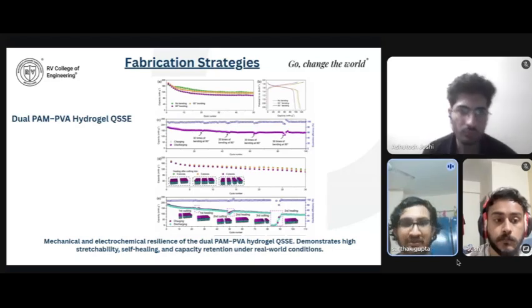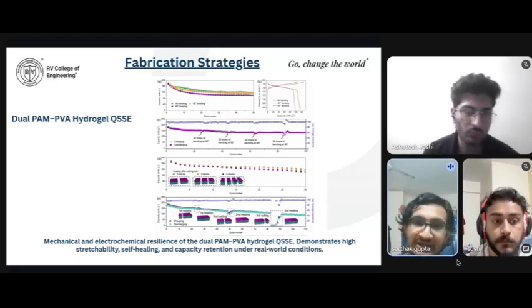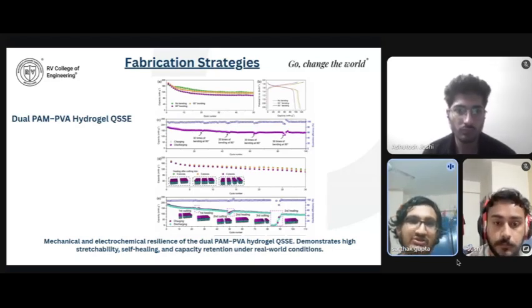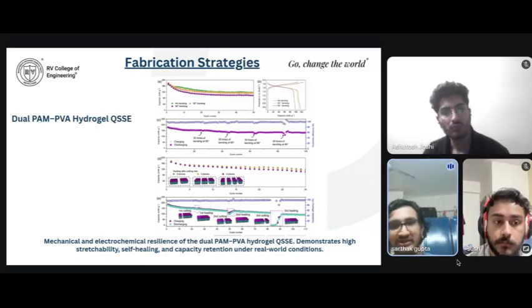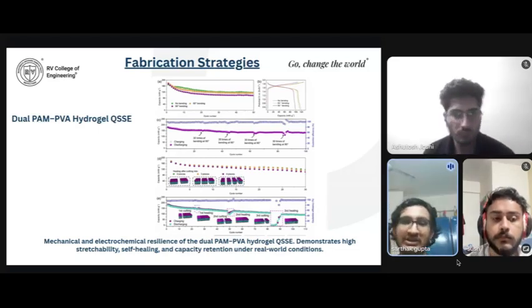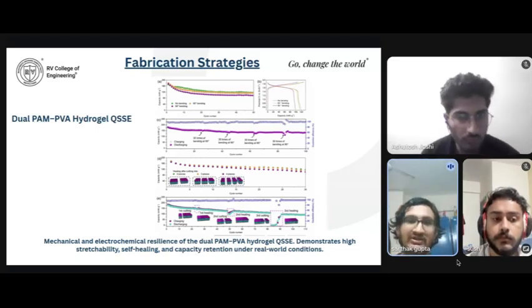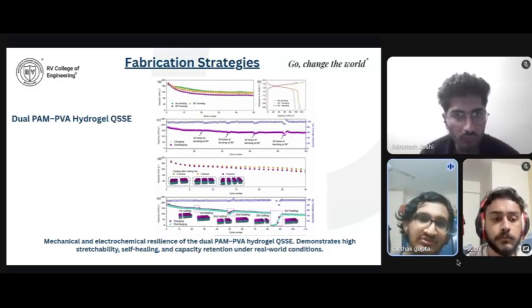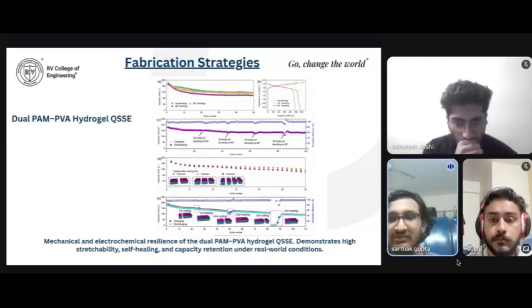Then coming to the last part, which is multiple cut-heal cycles, which is the dynamic nature. Basically, after each cut there is a small drop in capacity, and after healing, capacity recovers almost fully. In the graph, you can see that when it recovers, it almost recovers fully. Even after the third cut and healing, performance remains highly stable.